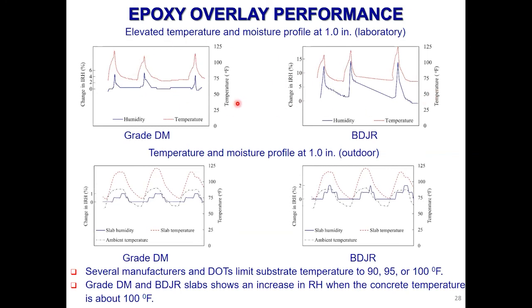And this is within like the first 100 days, so 150 days. But when the concrete gets matured, most of the moisture is used for the hydration purpose, because these slabs were all sealed around except for the overlay on top. That means the entire specimen is sealed, including the bottom. So there's no way to get additional moisture into the specimens. So with the age of concrete, we can see a very small increase in moisture content even with high temperature. So we see some better performance as concrete gets older, but still we see the lower bond strength.